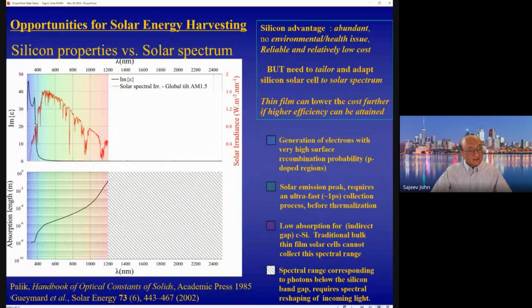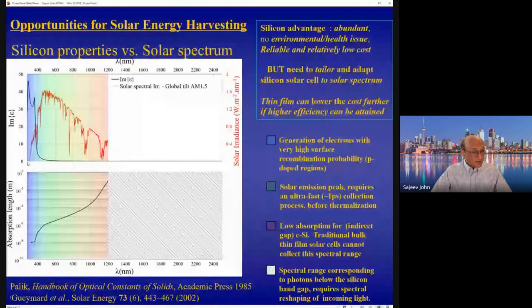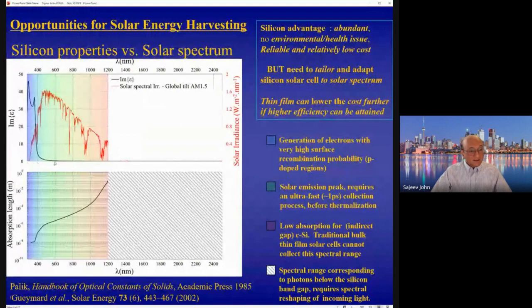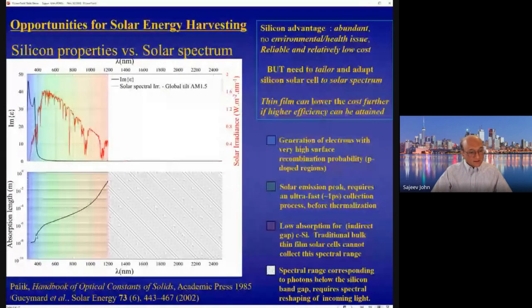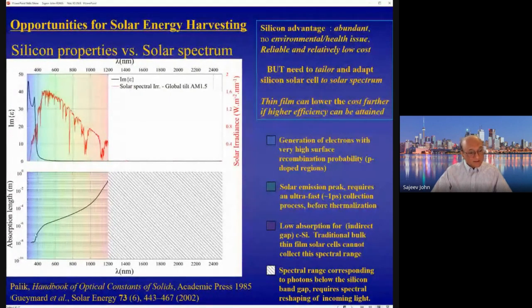As you can see, silicon absorbs very well below 400 nanometers. There isn't very much sunlight there. And because of the indirect nature of its band gap, it is rather weakly absorbing for longer wavelengths. Here I've translated that imaginary part into an absorption length scale as a function of the wavelength. So at around or below 400 nanometers, the absorption length is on the scale of tens of nanometers, but then it becomes much longer as you approach the indirect band edge. That absorption length scale is on the scale of tens of centimeters.